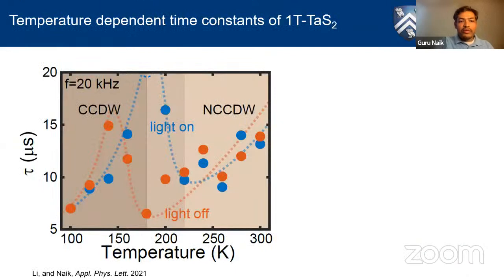We also characterized this time constant, so how fast these changes happen as a function of temperature. As we reduce temperature, just pick one curve. There are two curves here, one for light on, one for light off. There is a hysteresis because of thermal or photothermal effects. That's why we have these two curves slightly displaced, but they show qualitatively the same behavior.